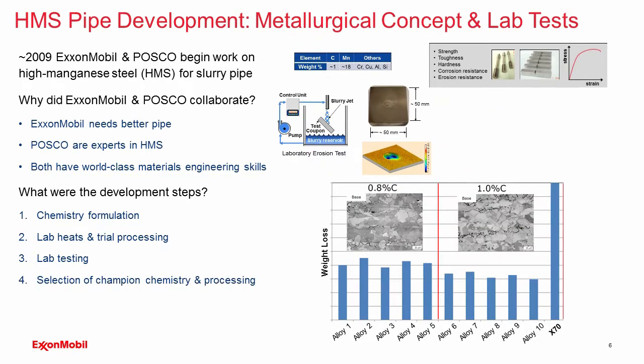And here you can see weight loss on the y-axis and a number of the alloys, the experimental laboratory alloys, on the x-axis. And down there on the right-hand side, X70, that's the traditional grade for slurry pipelines, and the high manganese alloys are performing much better than the X70. And so in the end, we selected a champion chemistry and processing route and have scaled it up to commercial production. Now let me talk about the mechanism of wear resistance in these high manganese steels.